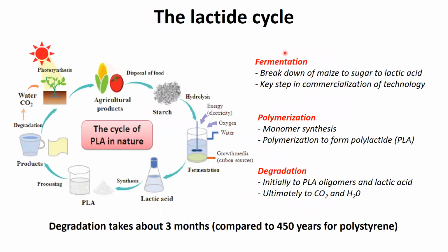If I just talk you through the lactide cycle, essentially lactide comes from the disposal of food and agricultural products, which you can reduce to starch. You can then hydrolyze, ferment, and form lactic acid. You can then use that to polymerize polylactide to make products, then you can degrade to water, CO2, and again back, so you basically have this cyclic nature of PLA. The interesting thing is the degradation of a lump of polylactide takes about 3 months compared to 450 years for a comparable piece of polystyrene. So this really is starting to be able to degrade under much milder and much quicker conditions.